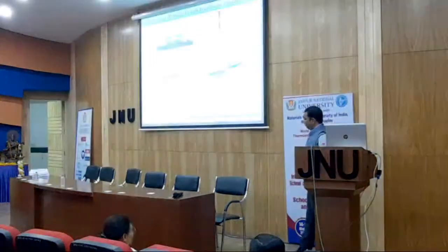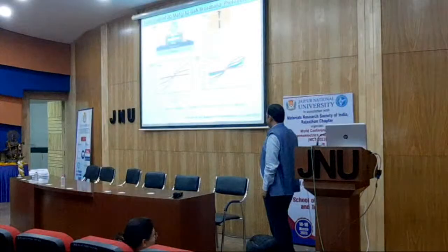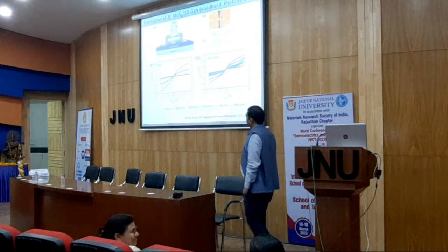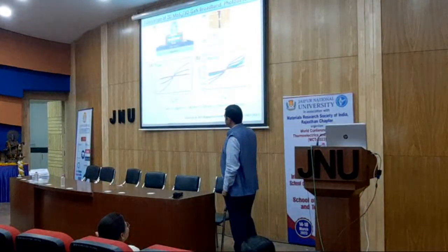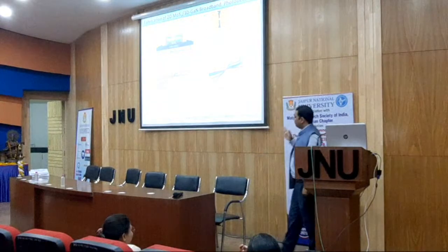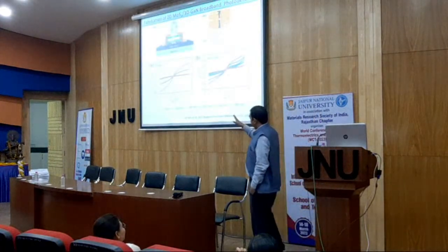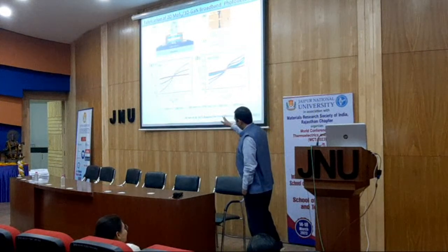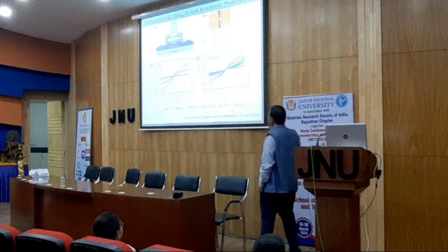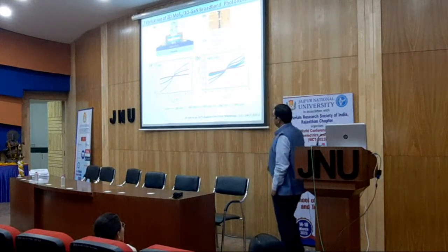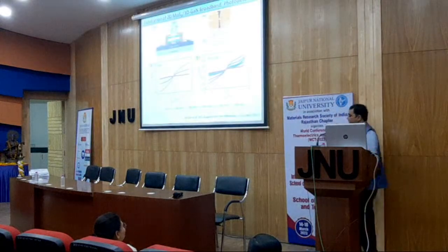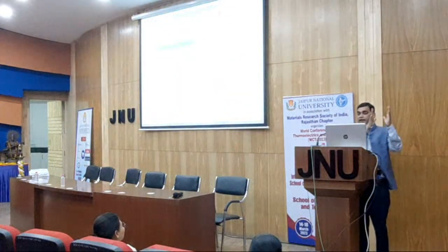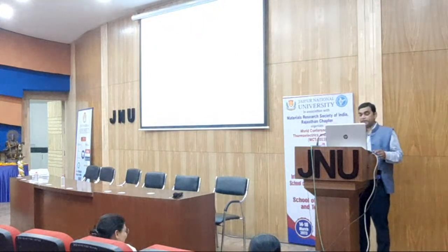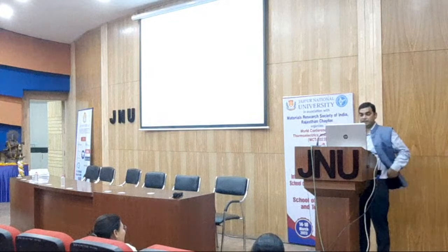These devices were tested under the influence of different optical radiation starting from 280 to 850 nanometer. The bare gallium nitride based device is showing very good response to 280 to 365 nanometer optical illumination. But while testing this bare device under 455, 565, 850, which is coming from visible to IR range, the device is not responsive. While MoS2 gallium nitride is responsive to all 5 optical radiations, it means we are getting UV to broadband in this particular device, and the response is clearly visible in terms of photocurrent for bare and MoS2.